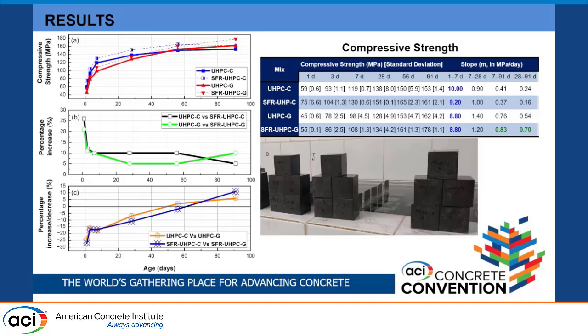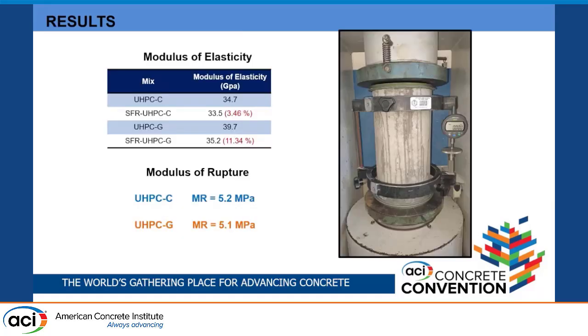So these are the compressive strength results. You can see the compressive strength development in the graphic that is in the top, okay? And we can see that the major compressive strength development is obtained in the first 7 days, okay? And in the bottom graphic, we can see that the presence of the vitrified clay gives higher strength since the age of 60 days, and that is attributed to the pozzolanic activity of the material. The modulus of elasticity in the case of the reference concrete decreases 3.46% in the concrete that has fibers, so the fibers lead to a decrease of 3.46%, and in the case of the green concrete to 11.34%.